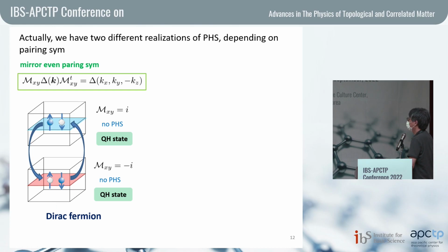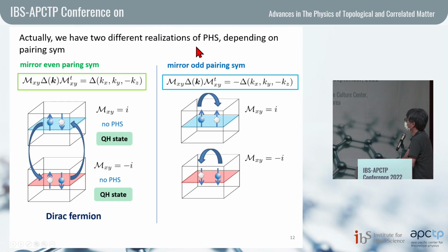But the situation can be different if you consider the mirror odd pairing symmetries. In this case, we have an additional minus sign in the transformation law for the gap functions, and the particle-hole symmetry is realized in a different manner. Actually, we can show that if you apply the particle-hole symmetry to the up-spin electrons, we have an up-spin hole in the same mirror subsector. And the same situation can happen even in the mirror minus subsector. So as well as the whole system, we have a particle-hole symmetry for each mirror subsector.